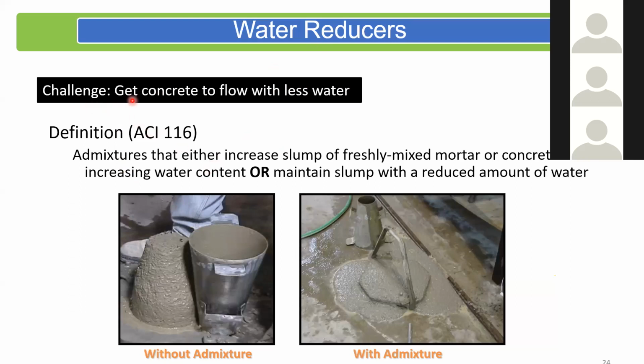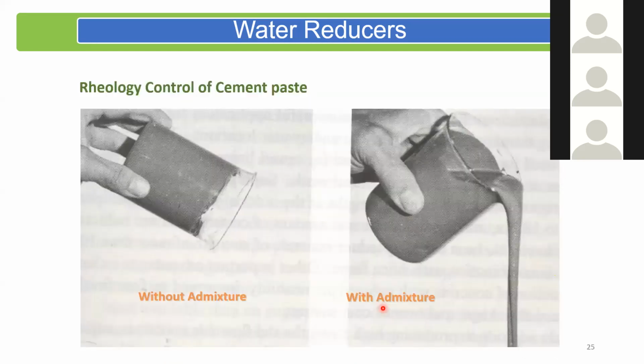Now, the challenge was to get concrete to flow with less water. And of course, without admixtures, as you see here, we basically get some slump, but with a little bit of water reducer, I can get this concrete to flow. So that was the early thought that went into making concrete that was strong, yet somehow be able to fill the formwork. And this is just to show you, this is rheology control, and I'll explain this a little bit later in a few of my other slides. This is cement paste without admixture. If I mix cement paste, let's say with a water to cement ratio of 0.32, 0.33, or even up to 0.36, it doesn't flow. It just is very tight. But the same cement paste with just a few drops of water reducer admixture starts flowing. So that is what these complex chemicals do. They enable the flow without having to add water.